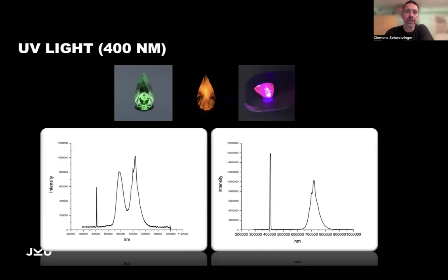Of course, being a scientist, we recorded the spectra. And what you can see here, let's start with the right one. This is a pure fluorescence of chromium. You see here the 700, or it could also be vanadium because it's very hard to differentiate between these two. And here on the left side, we see the same chromium or vanadium band, but also there's a second band. And this separates them. These two mix together. Therefore, we have the pure red, pink here. And here we have the pink mixed with yellow that makes it orange.